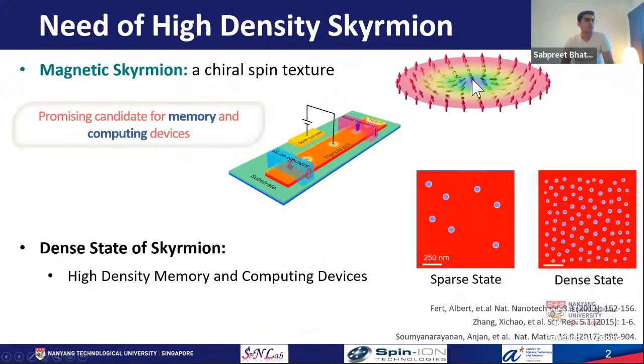Ideally, the skyrmions are considered to be these 360-degree domain walls. For the experimental studies, normally you have a substantial value of Dzyaloshinskii-Moriya interaction, which makes this bluish part as small as possible. Because of different values of DMI, you have three categories. One is bubble-like skyrmions, which are more than 1 micrometer. Then come skyrmion-like structures, around a few hundred nanometers. And then there are skyrmions that are sub 50 nanometer. It's one single domain with a continuous 360-degree domain wall. The skyrmions I am showing are around 75 nanometer, somewhere in between the actual skyrmions and the